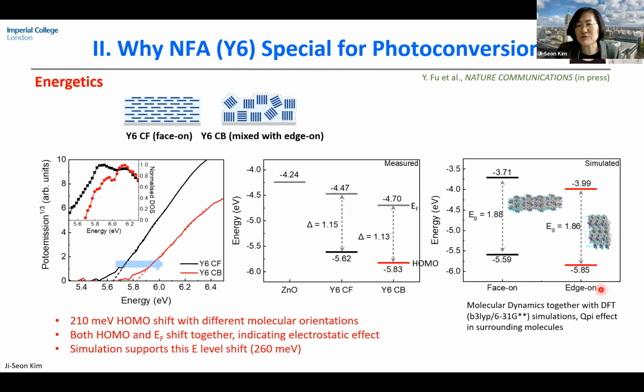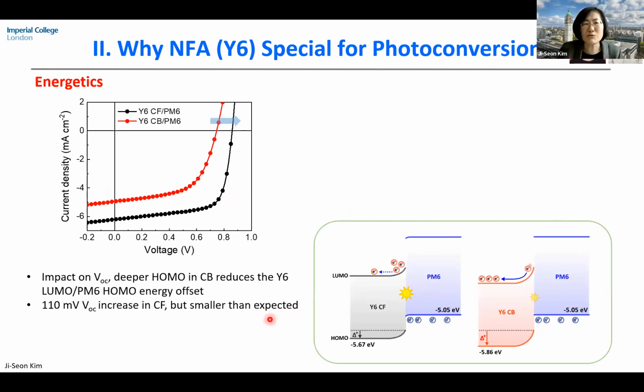And such energy level shift is also supported, quite surprisingly, very well with molecular dynamics. So when you put these differently oriented Y6 molecules using a solution-based process in a bilayer structure with the PM6, we observe a very strong impact on open circuit voltage, as expected, because different quadrupole effects will push down the HOMO energy level to a different level. So the edge-on structure pushes down more. Therefore, the gap between the LUMO of Y6 and the HOMO of PM6 will reduce, reducing the open circuit voltage as we observed.